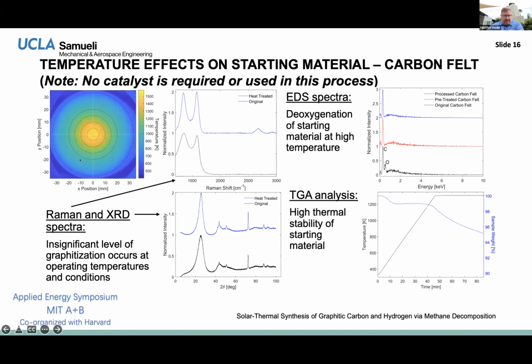Again, at the particular power setting that we used, sort of our default, this is the temperature field on the carbon felt. Like I said before, at the center it's a little bit above 1500 Kelvin, and this is the sweet spot. This is where a lot of deposition happens. And then on the periphery, which is actually the majority of the area, it's a much lower temperature, dropping down to probably 700 Kelvin at the edge of the carbon cloth. So a huge change in temperature across this very thin, 3 millimeter thick, porous material. What we do is a little bit of thermal pretreatment on the carbon felt. This just shows that we go through the process and reduce some of the material, but it actually starts out in pretty good shape to begin with; this is just for consistency.